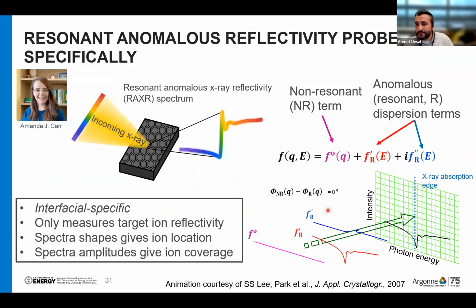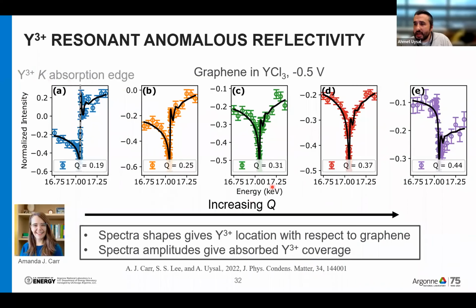And with the RAXR measurements, what we do is we are tuning the energy at a fixed Q. We go to a fixed reflection, and then we are changing the energy, and basically we are doing an energy scan around the edge. And by looking at how the phase changes between the resonant and the non-resonant signal, we can determine the position of the ions from the surface and also the coverage directly. I'm just showing some representative data of RAXR from the graphene interface. And as you can see, by scanning different Q values, different reflection angles, we can see a very clear phase change, and that helps us to determine the coverage and the position of the yttrium ions at the interface.